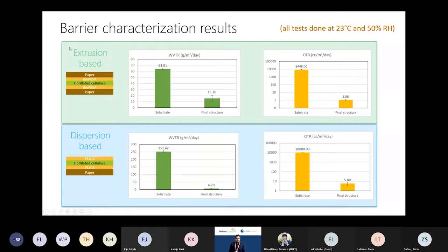And if we look at the barrier results for these, so for the extrusion-based structure where we have paper, bio-PBSA and fibrillated cellulose combination, you can see that the water vapor transmission rate for only the bio-PBSA coated paper was around 63. Of course, bio-PBSA was contributing to that barrier, but then when we had the full structure, we were able to bring it down to around 15. So this was a good improvement compared to just the bio-PBSA coated paper.